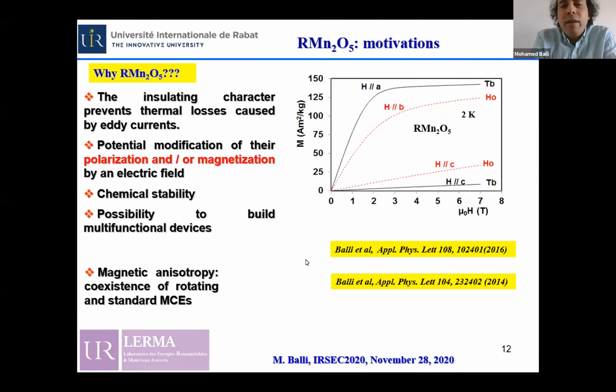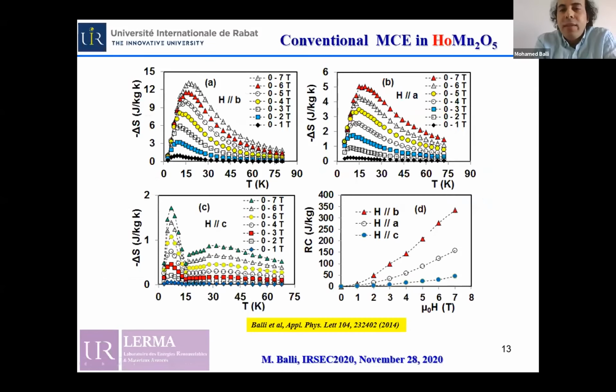Here is given the magnetocaloric effect in terms of the entropy change along the main crystallographic axis of the HoMn2O5 compound. As you can see, the entropy change generated by this compound presents a strong anisotropy. We can see that these materials involve a giant magnetocaloric effect, particularly along its AZ axis corresponding to the B direction.